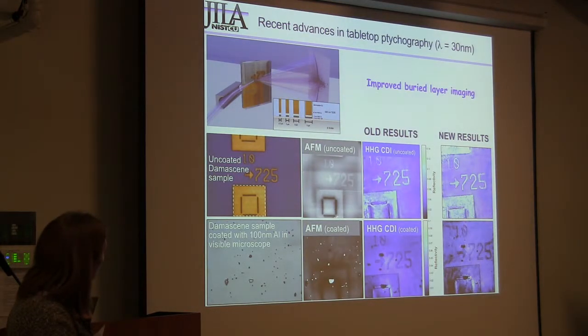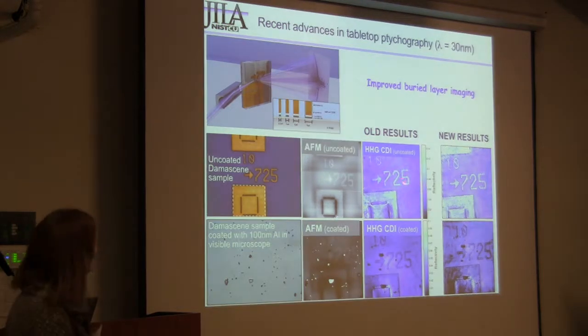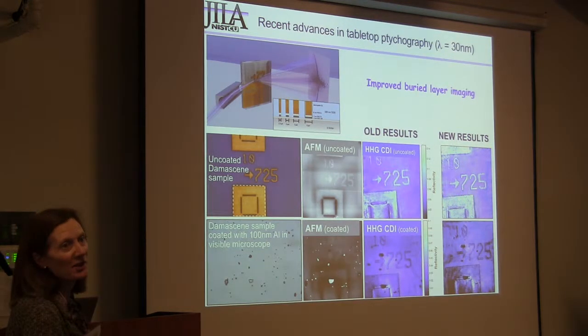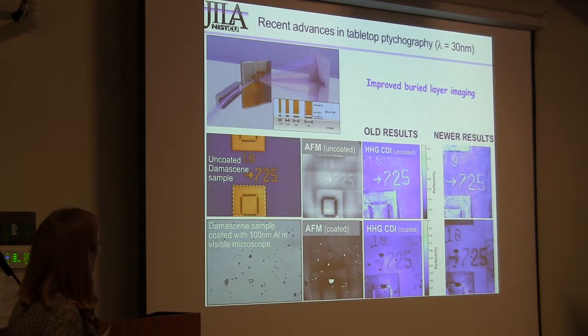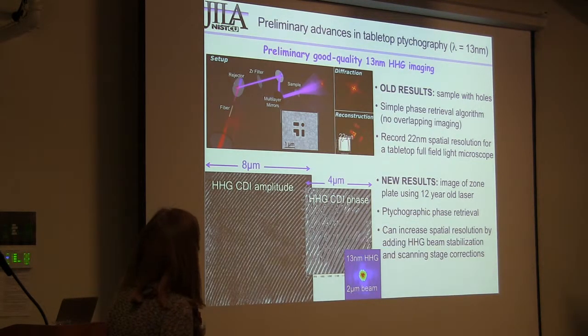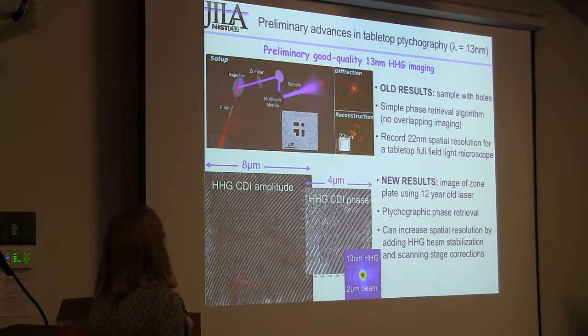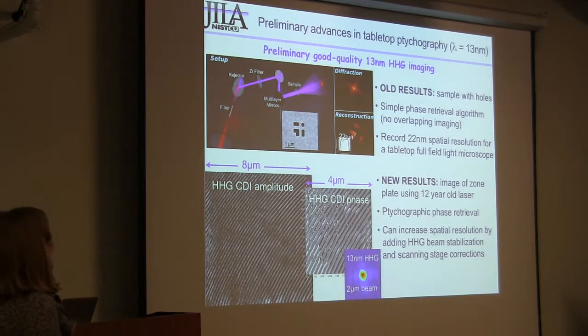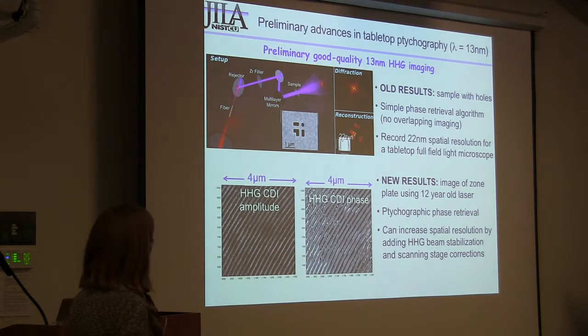And then, more recently, the students have been just working on refining the images. If I put them side by side, you can see that we're getting better at the algorithms. This is the original algorithm. Now, as we put more and more corrections in, you can see they're getting sharper and sharper. These are very preliminary data, just showing we're looking at more and more interesting samples. Now, this is a harmonic image of a zone plate, just showing that we have a nice beam. These are still very preliminary.